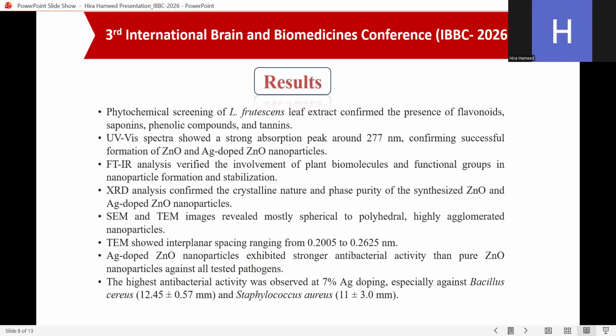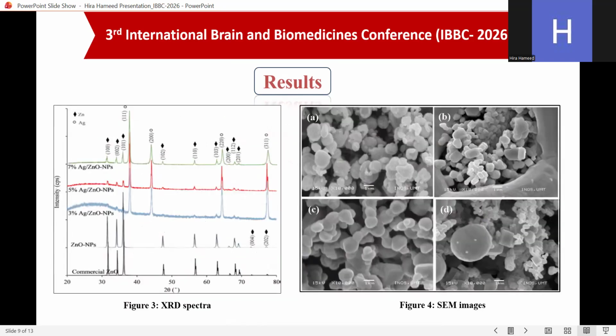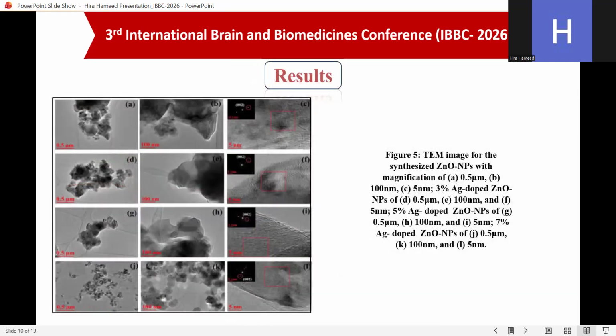Then we did XRD analysis. It confirmed the crystalline nature and phase purity of synthesized zinc oxide and silver doped zinc oxide nanoparticles. SEM and TEM images revealed mostly spherical and polyhedral, highly agglomerated nanoparticles. Here are the SEM images and here are the TEM images. We can see the different values at different levels.